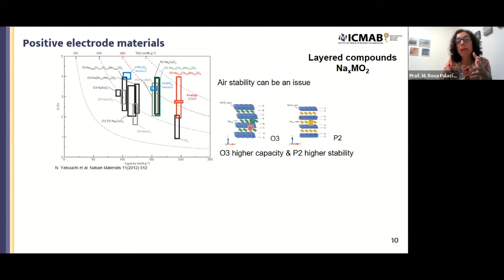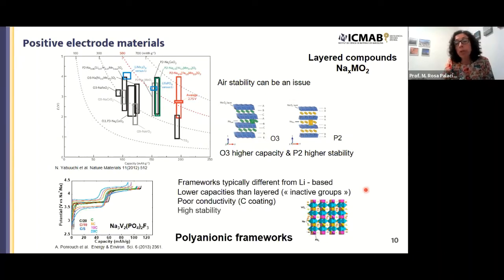And for the case of sodium-ion, one can form very similar phases, but in this case, the coordination is sometimes also prismatic as a result of the larger radius of sodium. So in this case, those materials are really very similar. Air stability can be an issue, but still. But then for 3D structures, typically